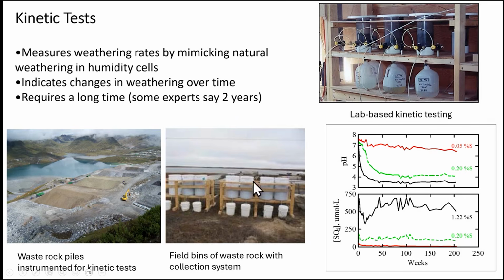And the kind of information you get is shown in the lower right here. This is for 3 samples of different amounts of sulfur. pH and dissolved sulfate is plotted, and not surprisingly, the sample with the highest amount of sulfur produces the most sulfate and also has the lowest pH. So it's got the highest amount of oxidizing sulfide minerals. And this is shown for quite a bit longer than 2 years.